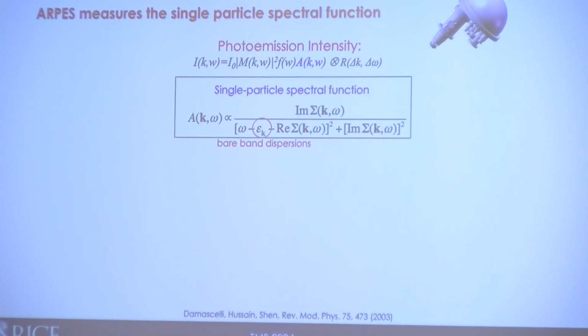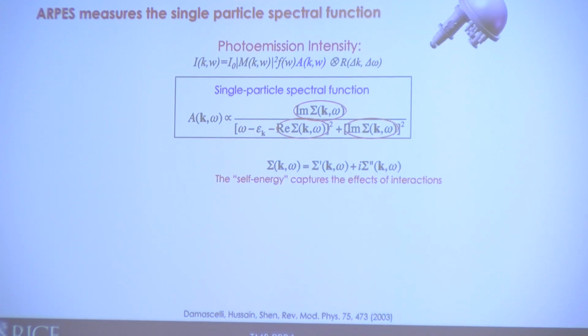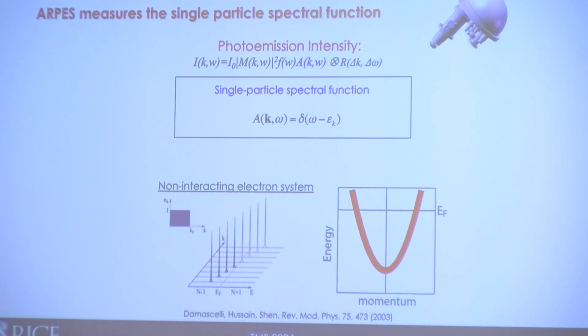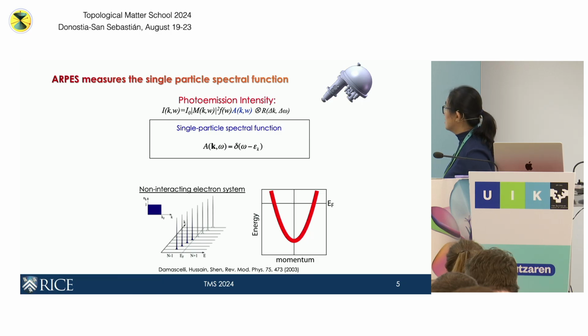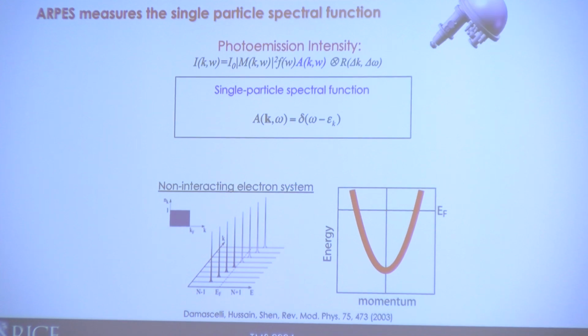So, of course, we measure these energy dispersion relationships. But in addition, any effects that change your electronic states can be captured in these self-energy terms. There's a real part and also an imaginary part. Just to show you what kind of information we can get from this, imagine you have a non-interacting system, I think Lenny already showed this in her talk. So you will get these essentially infinite lifetime states, because they're not interacting, and this is the dispersion that you will see.